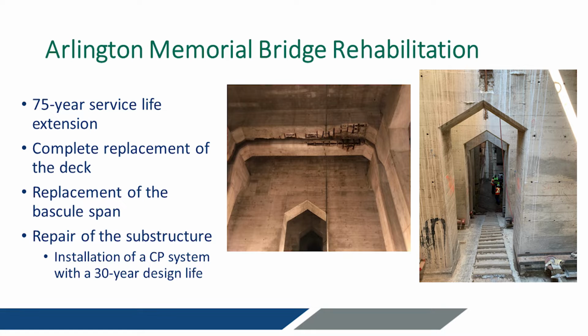As you can see here, there is some corrosion damage on the cross walls. There are expansion joints at every pier, and chlorides from de-icing salts in this area get down into the expansion joints and cause corrosion deterioration. So they wanted to install a cathodic protection system that would last at least 30 years to extend the service life of those elements.